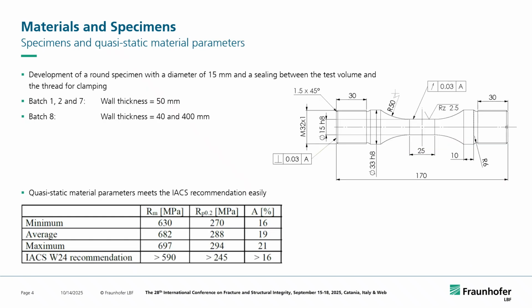After the specimen removal, we made some quasi-static material investigations. Here on the lower left side, we see the results, the minimum values, maximum, and the average, and also the IACS recommendation, the minimum values that are recommended. And we see that, especially in the average value, we are far above those values for tensile strength, yield strength, and also the elongation. We manufactured fatigue specimens from those batches, from those plates and designs, and we have then a batch 1, 2, and 7, which is referring to the 50mm wall thickness of those two bars that I showed you in the last slide, and we have a batch 8, which contains specimens taken from 40mm and 400mm wall thickness from those larger blocks.